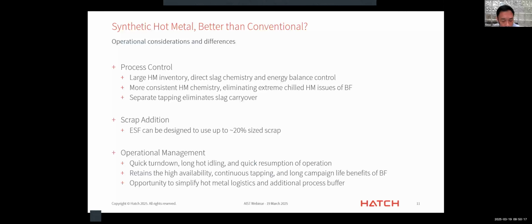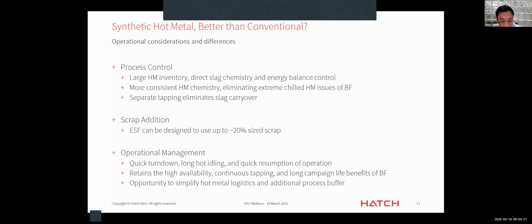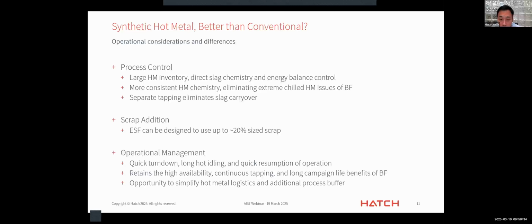Is there some sort of optimization opportunity there where you use more of the scrap in the ESF and have a lower carbon hot metal for the BOF that allows your blow time to come down, for example? So there is a lot of opportunity to optimize the overall operation based on the characteristics of the hot metal we produce and the ability to control it.